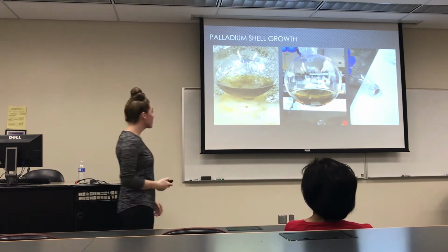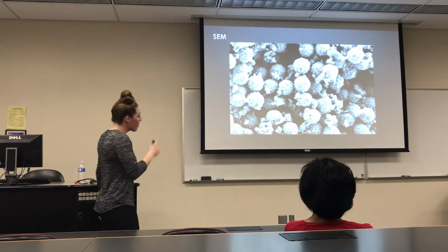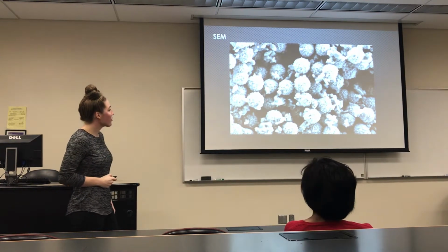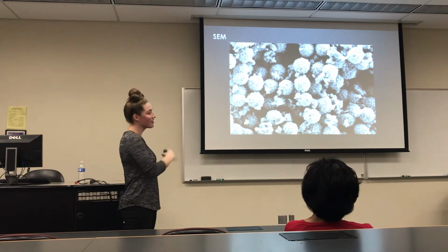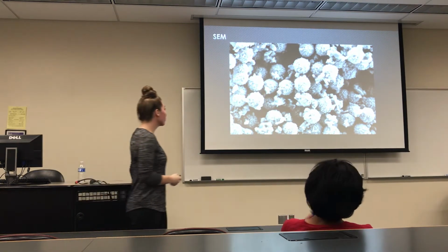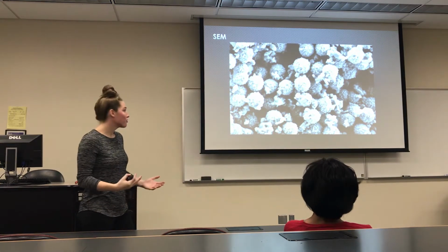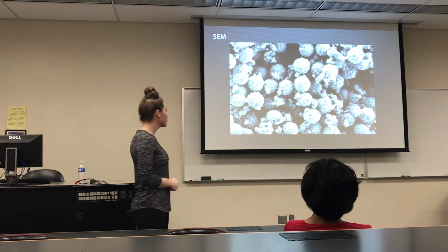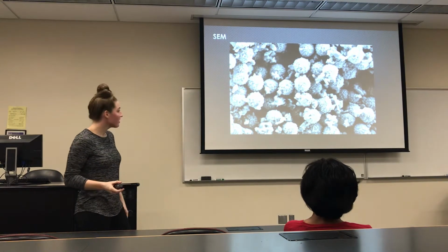We sent this one out to Miami as well, and we did get full coverage on the very first try. But there is a lot of unreacted palladium within that image, so that probably speaks to the fact that the chloride solution that I made was too concentrated with that metal. So this could be a future project that students could work on with respect to electrochemistry, as I mentioned before, using it as a catalyst for those types of techniques.